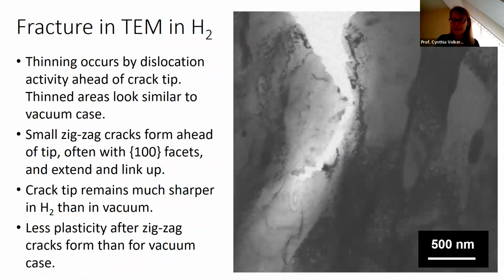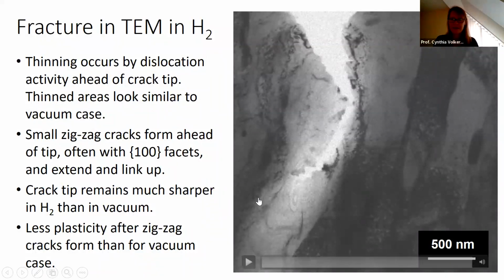And this is something that Lynn observed not just one time, but in several specimens, and of course in different grains as the crack moves through the specimen. So what one is seeing is that the thinning occurs as before due to dislocation activity, but then ahead of this crack tip, instead of holes opening, we form these small zigzag cracks. They grow and then link up, and that leads to propagation of the crack. And so the crack remains sharp, even though there has been significant thinning to begin with.